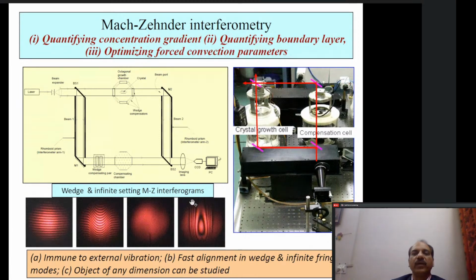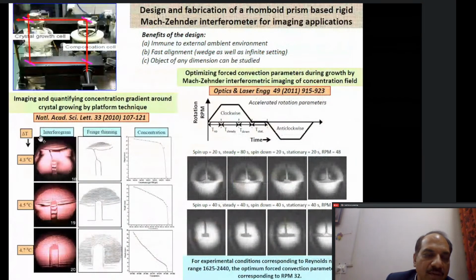Now when a crystal is growing, the refractive index of the solution around that crystal will continue to change, and because the light beam is sensitive to changes in the refractive index, you will see changes in the fringe pattern. That fringe pattern is then correlated with the growth parameters, and finally with the refractive index of the solution from which the crystal is growing. And then we correlate what changes were occurring in the solution during the growth, which have resulted in either good quality or bad quality of the crystal.